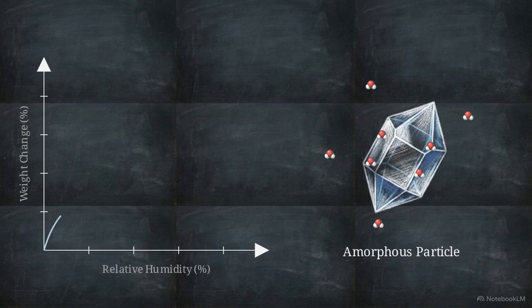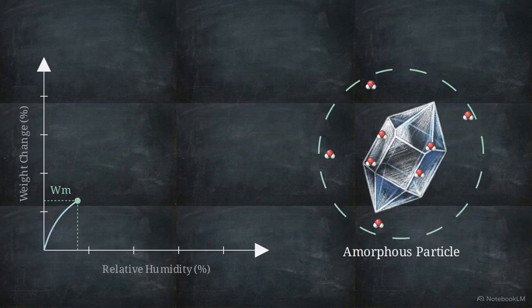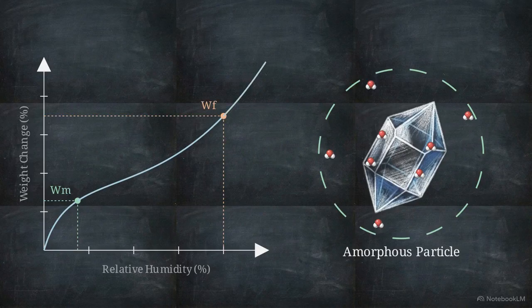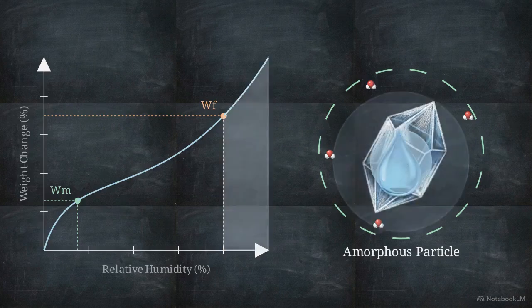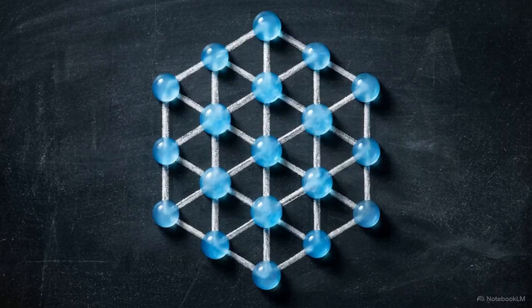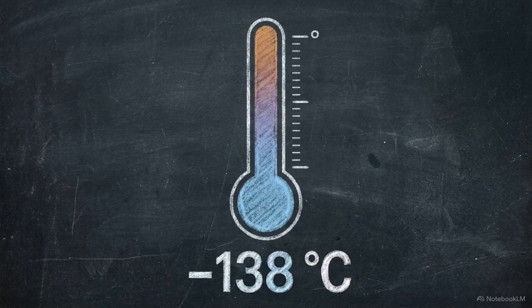The first inflection point, Wm, represents initial monolayer coverage. But once moisture crosses the second threshold, marked here as Wf, it behaves identically to free, bulk liquid water. At this stage, water becomes an extreme plasticizer. Because water has a glass transition temperature, or Tg, of roughly minus 138 degrees Celsius, it imparts massive molecular mobility.